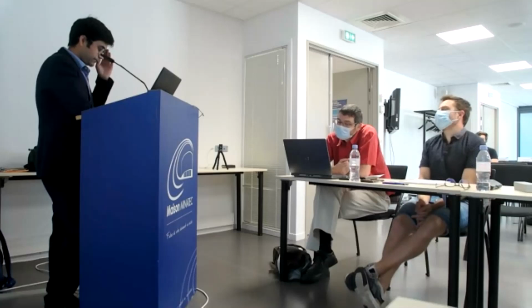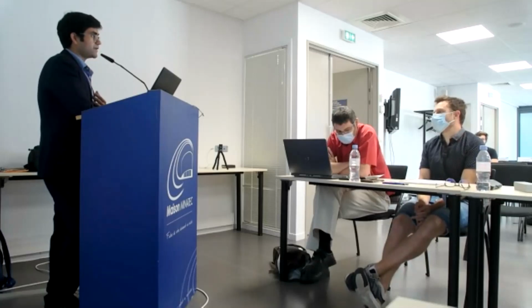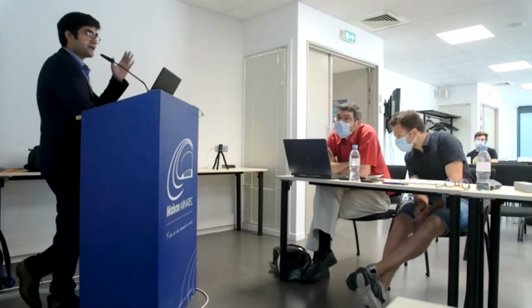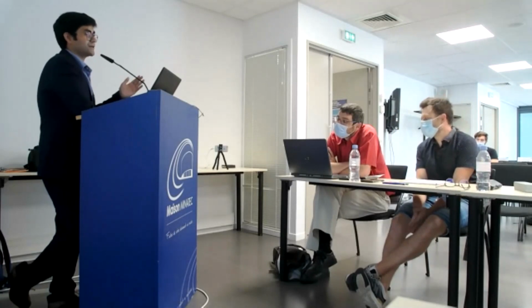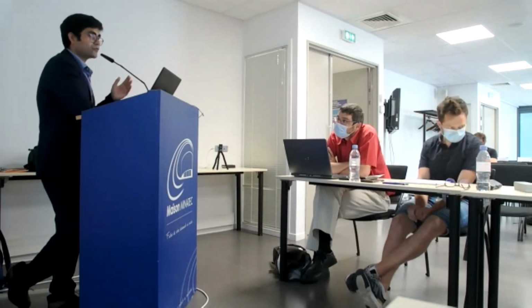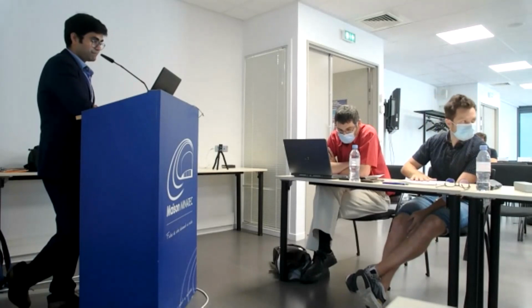In fact, according to my feeling, I agree that we clearly see a lot of precipitation along the grain boundaries, and controlling the solid-liquid interface energy, you might need to take into account individual aspects of these precipitates linked to the actual alloy composition. So I agree with that.